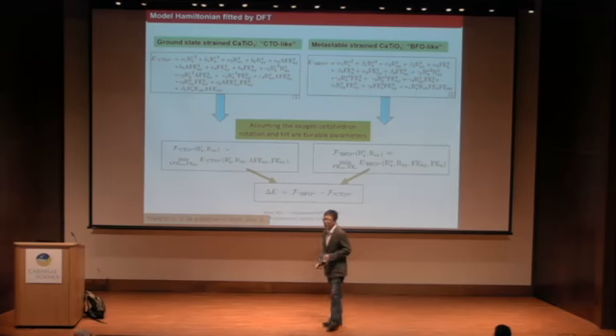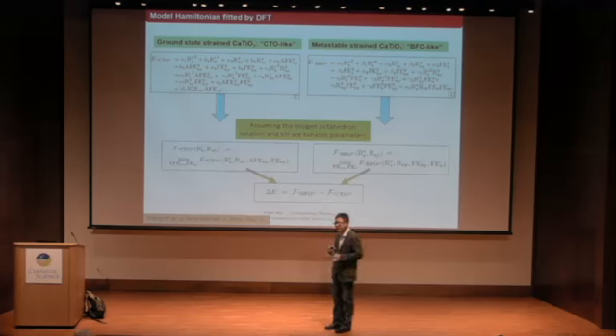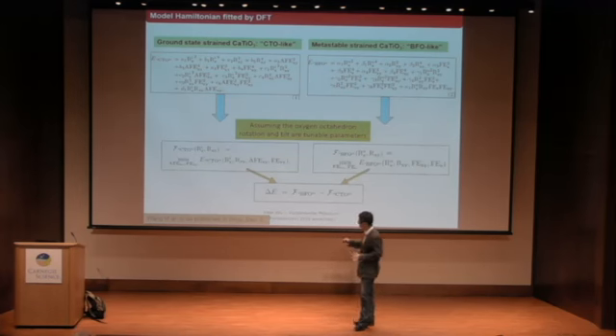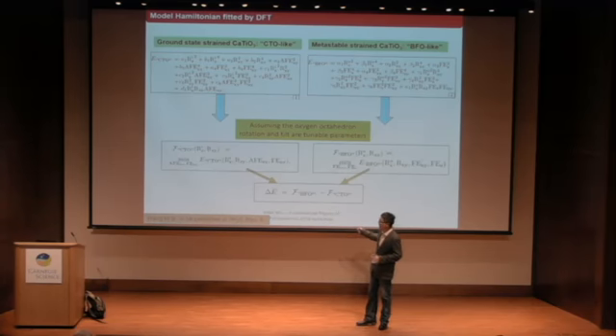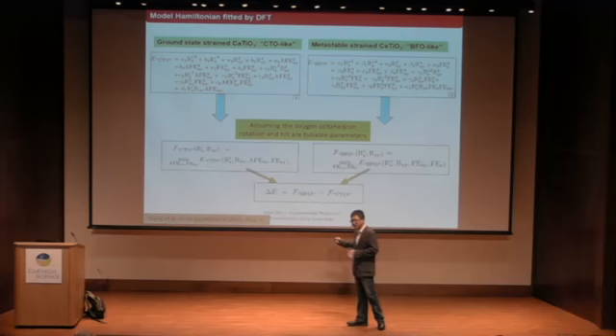In experiments, we observed that what happens is we suppress moderately the antiferrodistortive rotation and tilt. So naturally, we can consider that rotation and tilting can be adjusted by experimental conditions.